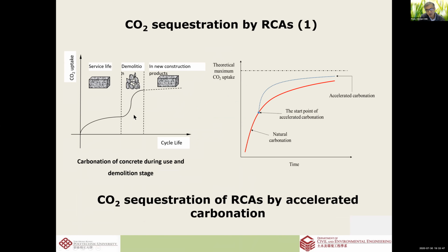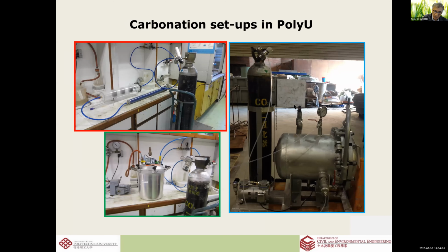This illustrates that this carbonation actually occurs naturally, but when we crush the surface layer of concrete, when we demolish it, the surface area becomes much larger because of the exposed area after crushing. And then when we try to accelerate the carbonation artificially, through what we call the accelerated CO2 carbonation process, we can produce new product and capture more CO2. So what we try to do in our lab is to use accelerated carbonation processes. Of course, in our lab, we first of all use 100% CO2 from a cylinder, and then we carbonate it using different pressures and also under atmospheric pressure, like a flow through.